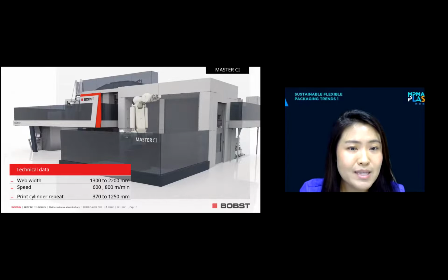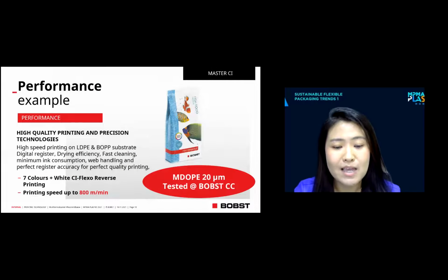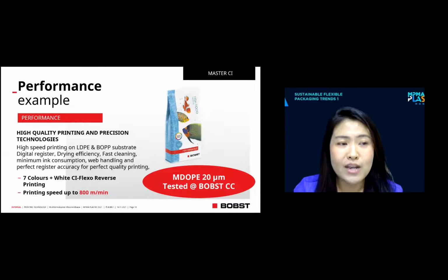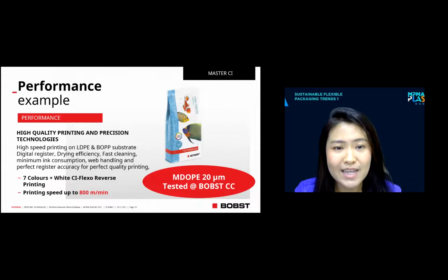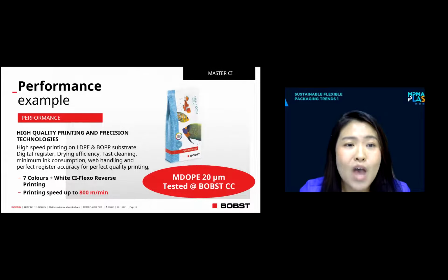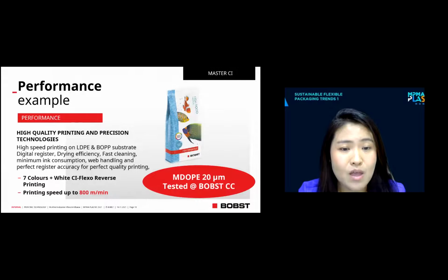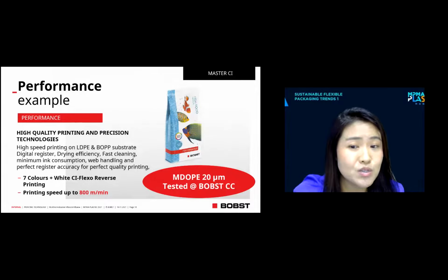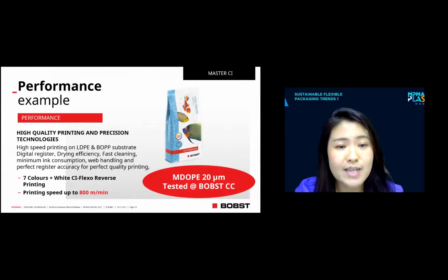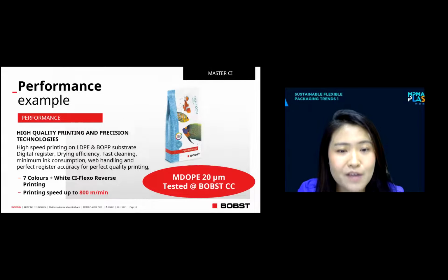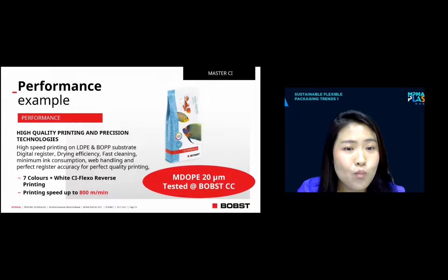But with the high speed, we also have to ensure that the higher capacity and the best web handling are perfect. With our performance on the Master CI, we talk about MDOPE 20 micron with 7 colors plus white. We talk about a production speed of 800 meters per minute. And I think not only can we handle this properly, but our perfect printing quality is also available on this model.